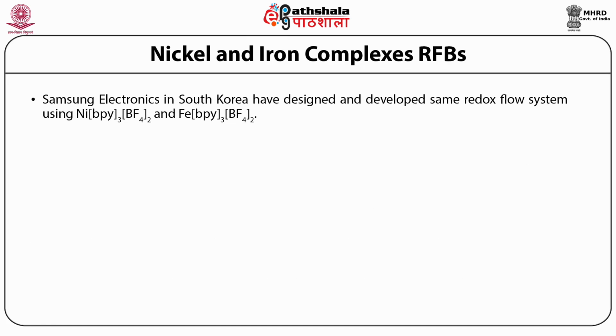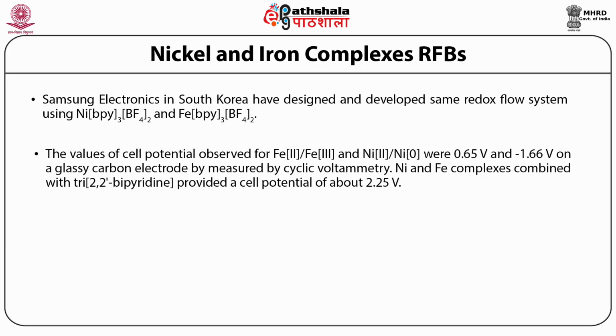Samsung Electronics in South Korea have designed and developed redox flow systems using Ni(bpy)3(BF4)2 and Fe(bpy)3(BF4)2. The values of cell potential observed for Fe2+/Fe3+ and Ni2+/Ni0 were 0.65 and minus 1.66 volts on a glassy carbon electrode, measured by cyclic voltammetry.